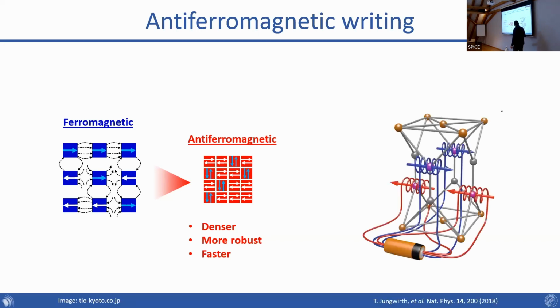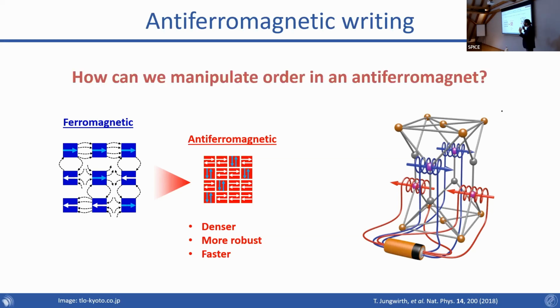But the difficulty, and I love this picture from this review article from Thomas Jungwirth, is that it is difficult to couple to antiferromagnetic materials because you cannot use uniform magnetic fields, for example. In principle, what you would need is some kind of an effective magnetic field that would alternate on each atomic site. Okay, so this is quite impractical to achieve in this particular way. And so I guess what we're all interested in is how we can manipulate order in an antiferromagnet, how we can do this fast, and how we can do this robustly, right?